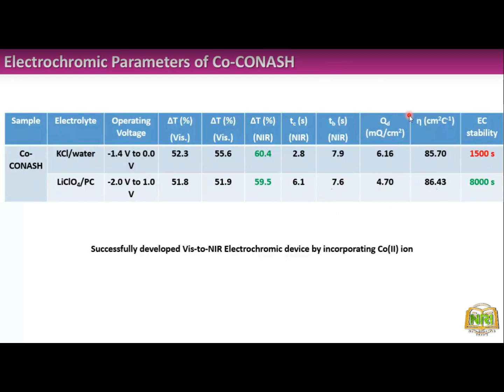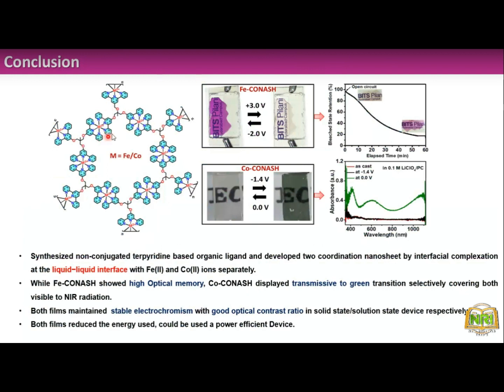So finally, what we did: we prepared a non-conjugated terpyridine-based tridentate ligand, and we allowed it to polymerize by 2 different methods. One is with iron, termed an iron coordination nanosheet, and this kind of compound shows good electrochromism. At the same time, it shows high optical memory compared to other reported metal organic polymers. And in the second case, we prepared a cobalt-containing coordination nanosheet, which shows visible to NIR electrochromism.